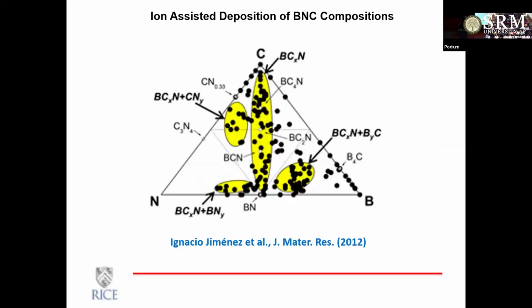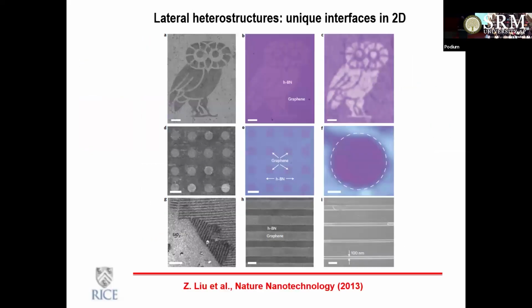But anyway, let me get to the point that I'm trying to make, and that is this idea that you can laterally engineer domains of boron nitride and graphene, same structure, same thickness, same lattice parameter, into seamless junctions, right? And once we saw that, we devised some techniques to do this in a much more controlled manner. So you can create engineered domains of boron nitride in graphene or graphene in boron nitride, which gives you all kinds of possibilities on a single atom thick layer, right? You can, for example, put a pattern of graphene in a boron nitride lattice, and you use that as an antenna. So once you grow that, you can peel the single atom layer and put it on other structures. So this is really engineering at the scale of a single atom thickness. So you can create all these beautiful structures.